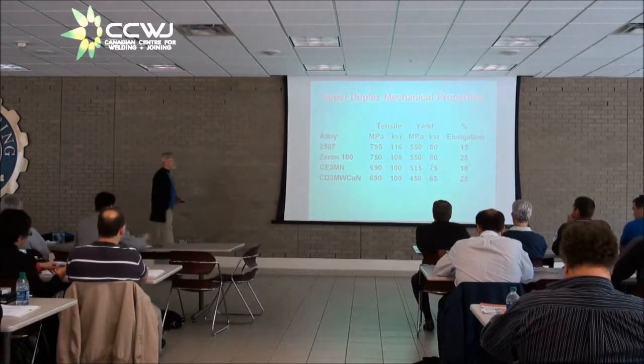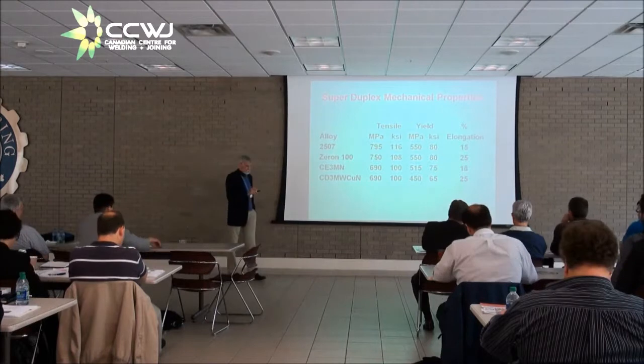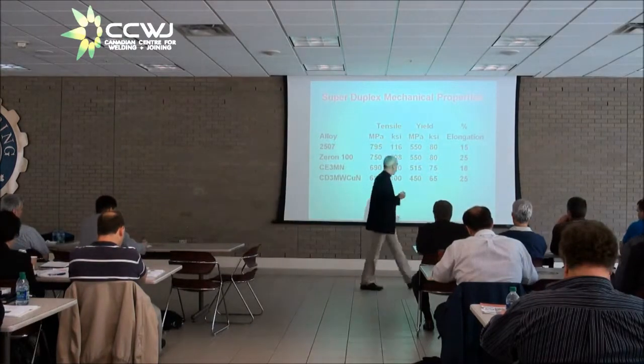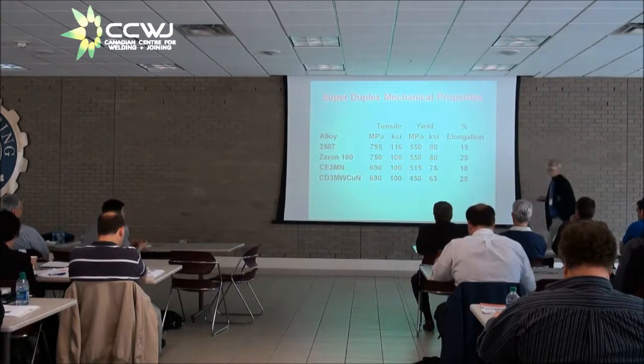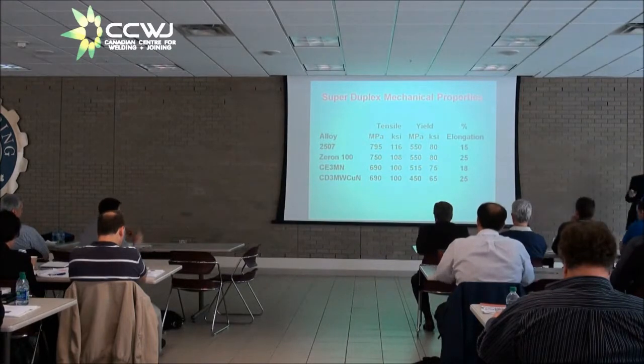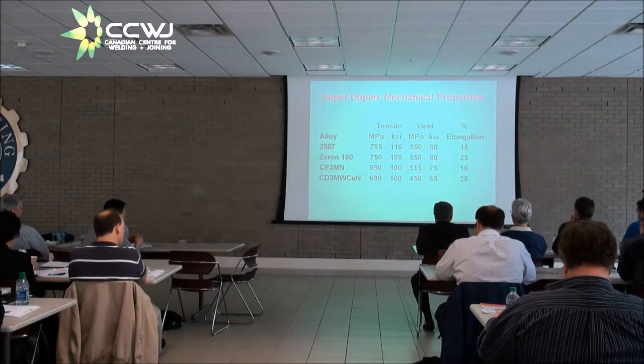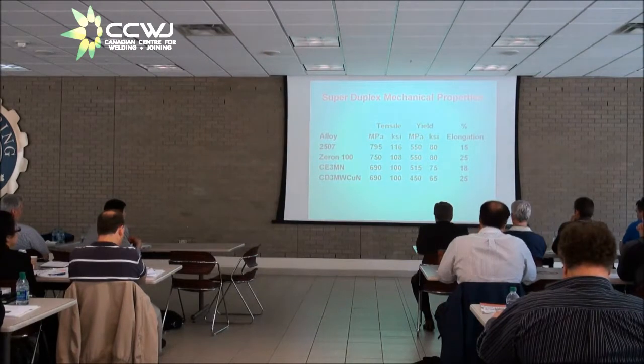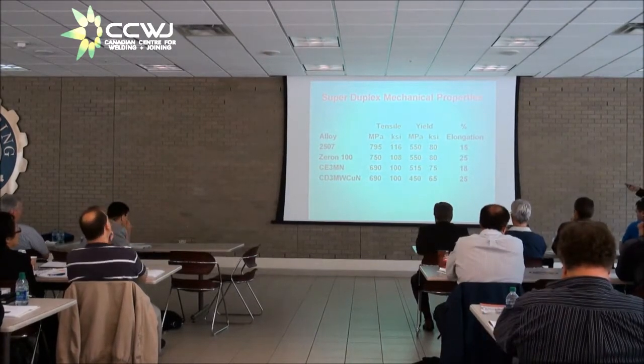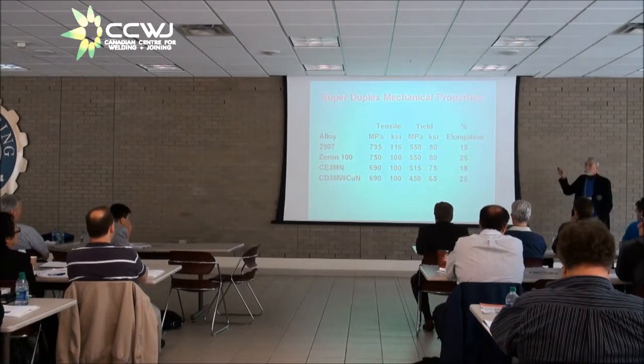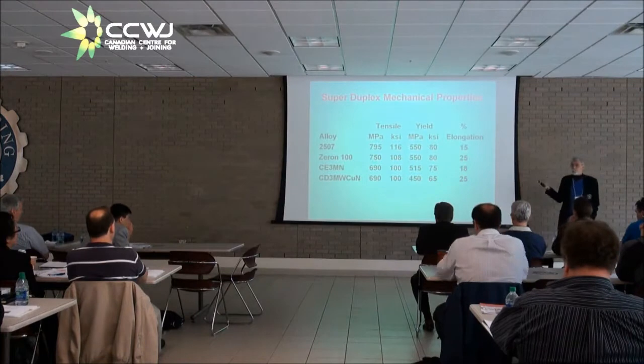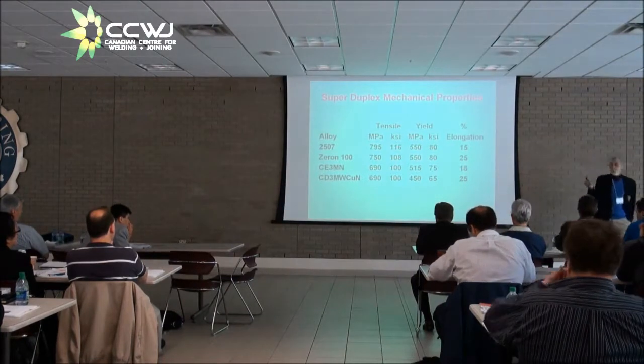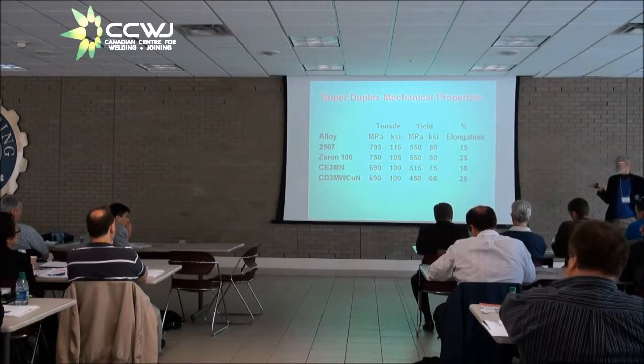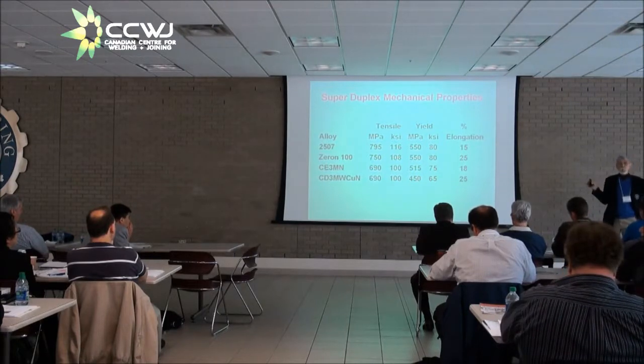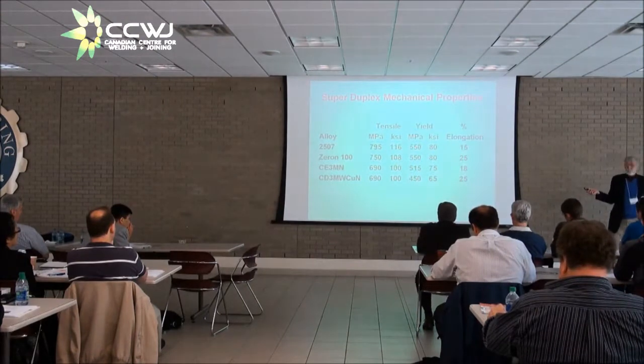Mechanical properties of the super duplex stainless steels are really outstanding. This is like HY80 steel with corrosion resistance. You're looking at 80 ksi minimum yield strength in the super duplex. You will notice that the yield strength numbers for the cast materials are lower. And that's caused by the fact that when you anneal the material, the microstructure tends to ferritize. And part of the strength in a duplex stainless steel comes from the layered structure of ferrite and austenite. When you lose that layered structure, you lose some strength. So you have to be used to that notion.